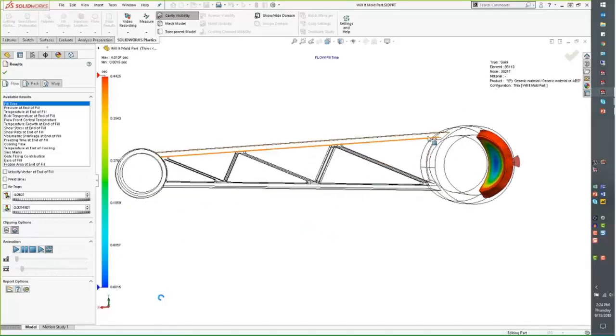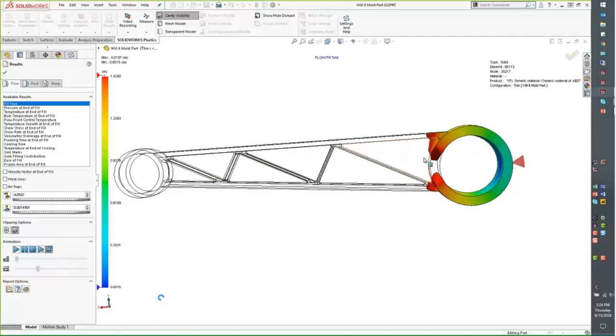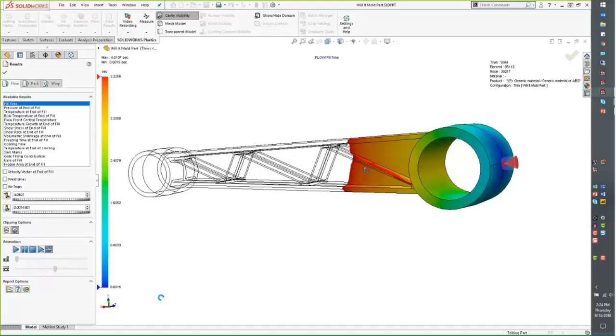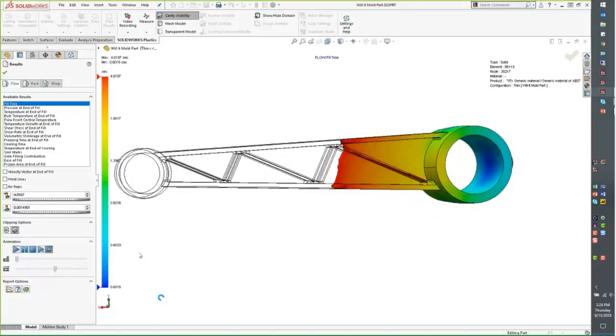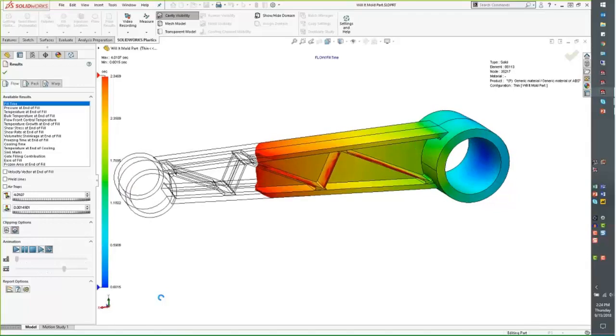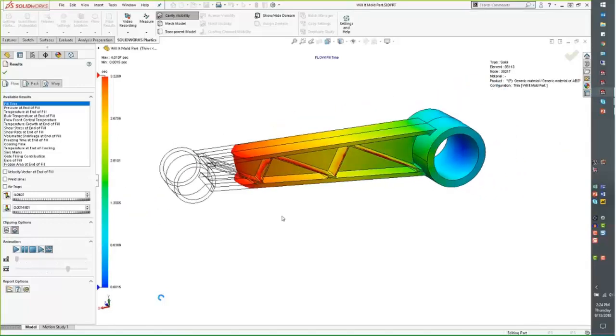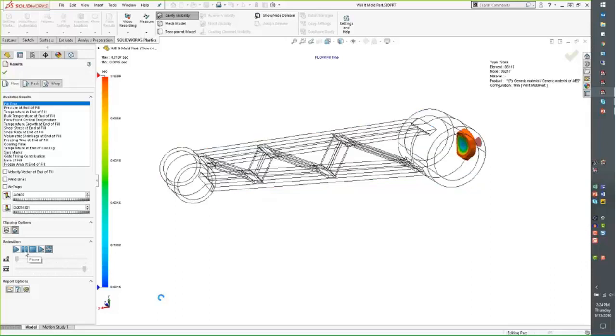And the reason that worked is that it's more uniform. So we're trying to push the same amount of material through these areas, and what you're going to see here is it doesn't really racetrack ahead of itself. It has a nice uniform movement as it fills through there. So we're getting a lot better feel for this kind of filling and moving through that. So it didn't change the injection location. It didn't change anything but the fact that I adjusted that geometry. So we feel pretty good about the fill aspect of this.